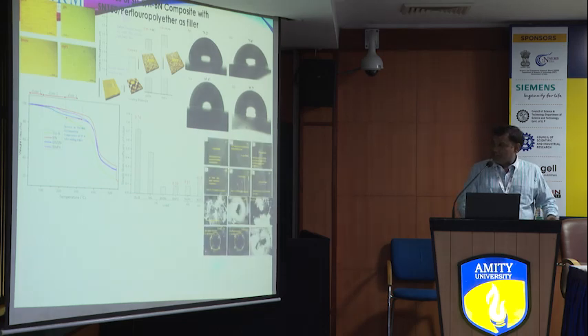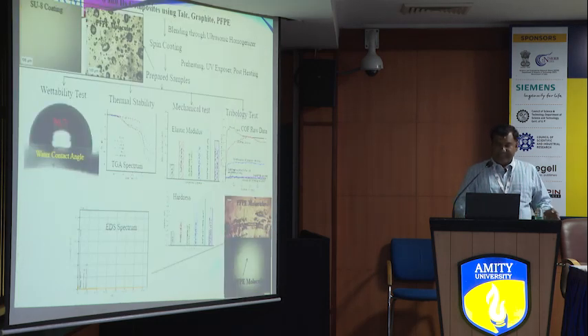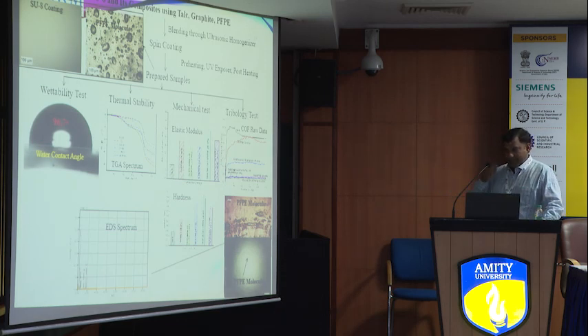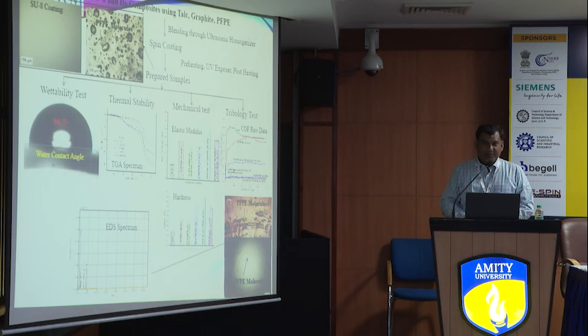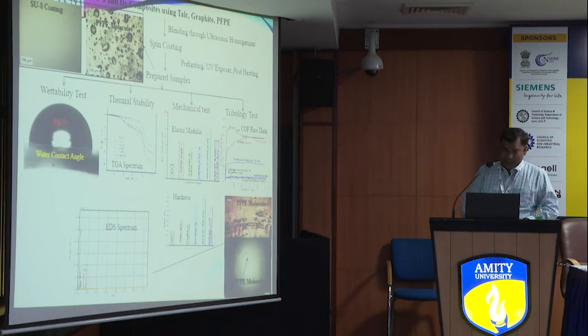So in the figure you can see here, the surface has not failed after adding the lubricant; there are just lubricant droplets. So that was one case. And recently I published one paper where, as I told you, graphite and talc give very good results. Then I added the perfluoropolyether, and you can see here that wettability improved by 96%, and you can